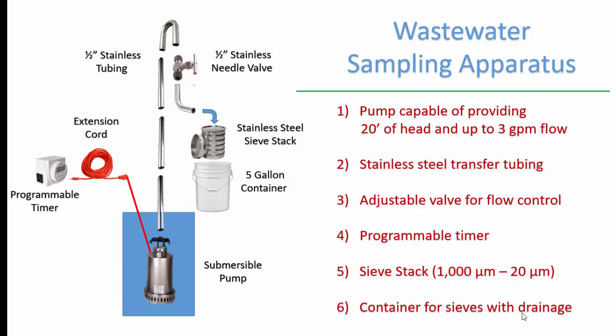Programmable timer. Now, at 3 gallons per minute, one of our influent samples will probably bind up and clog that screen mesh in about 3 hours. And so I would typically set my timer for 2.5-hour intervals. We'd go out, collect the material from the sieve, reinitiate the pump for another 2.5 hours, and we would do that over a 24-hour period. So we're getting a composite sample over a 24-hour period.